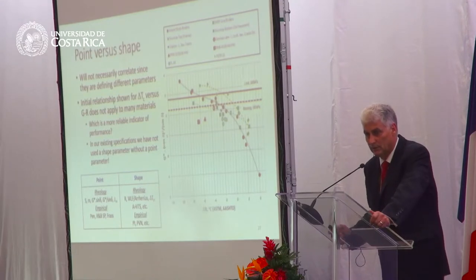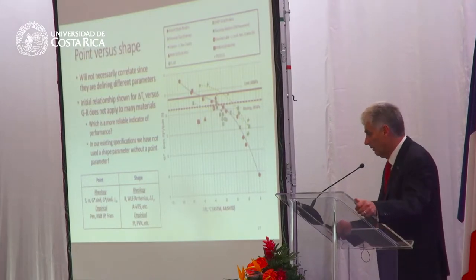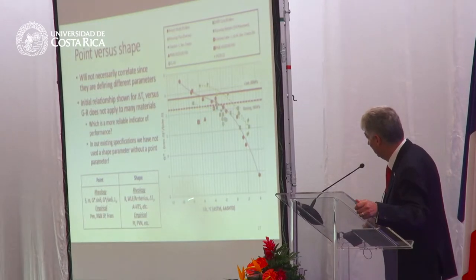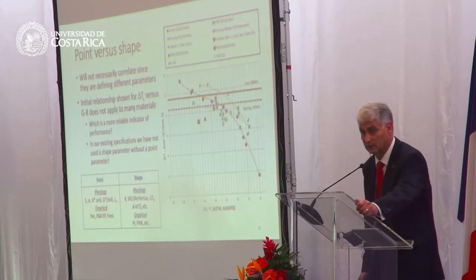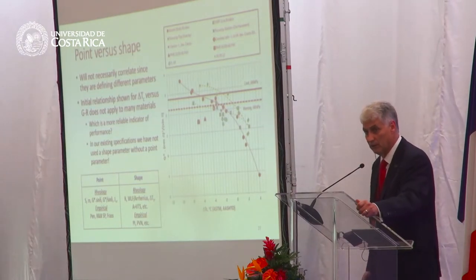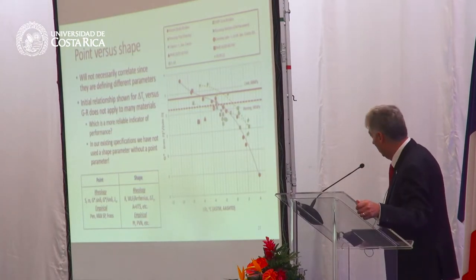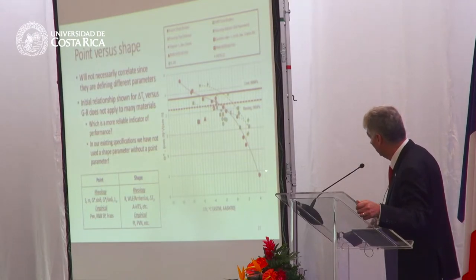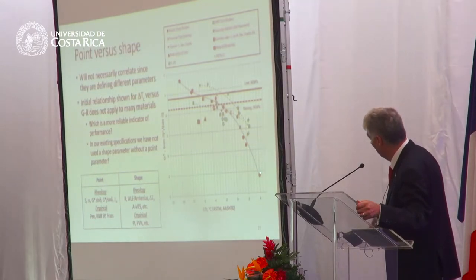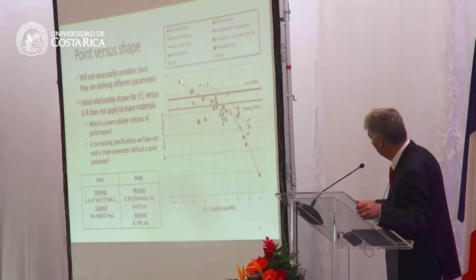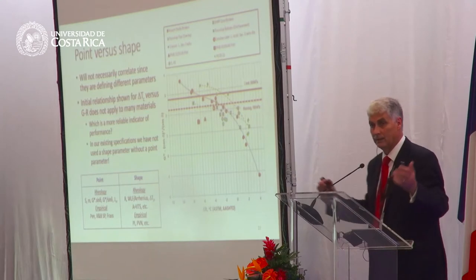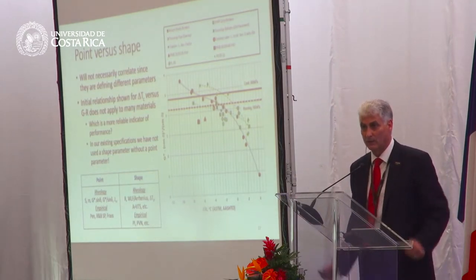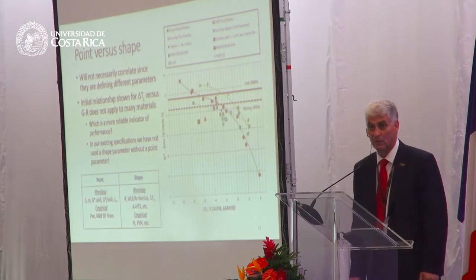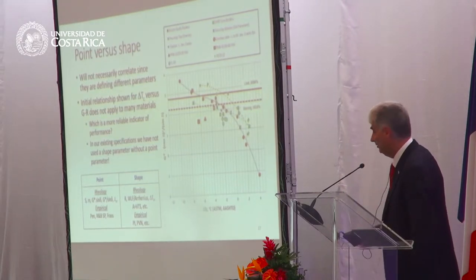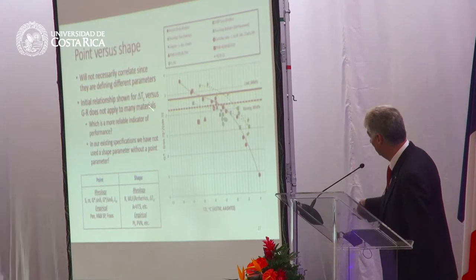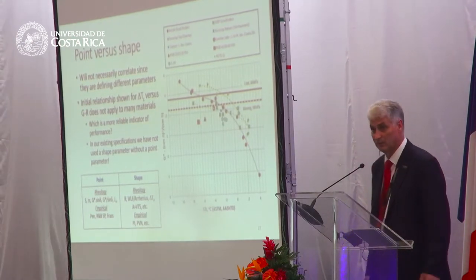This slide here shows the Glover-Rowe parameter on the vertical axis versus the delta Tc on the horizontal axis. When we did the original work, and this was work conducted by Mike Anderson about 6 or 7 years ago, published in 2011 in AAPT, he had these red data points here. You see these red data points and these lines here? And the answer that we thought we had was, hey, this is great. We have a single relationship for defining all our materials. Delta Tc is tied very nicely to the Glover-Rowe parameter, and we have a single relationship.